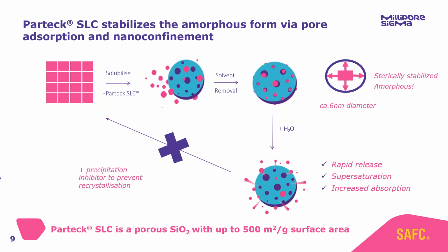So how does it work in practice? We take our poorly soluble crystalline API. We can use organic solvents to break that crystal lattice for us, so to do the hard work of breaking those bonds. We solubilize in an organic solvent such as acetone, ethanol, methanol. This concentrated solution of our API can then be combined with mesoporous silica, and exactly like a molecular sponge, that concentrated API solution is absorbed inside that mesoporous network.